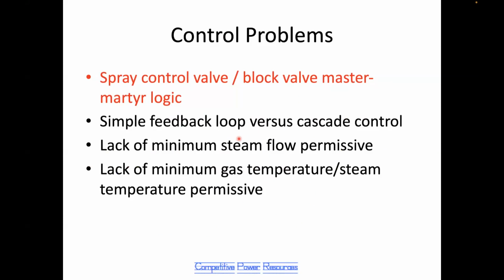When we have the block valve and the spray control valve, we need some kind of logic to tell those valves when to open one relative to the other. Most units use a master-martyr logic that tries to protect the control valve from damage. Anytime you open a valve with high pressure on one side and low pressure on the other side, when you first open that valve, you get a very high velocity flow through a very small area between the valve seat and the valve disc. That high velocity water in that small space will erode the seating surfaces and cause the valve eventually to begin leaking.